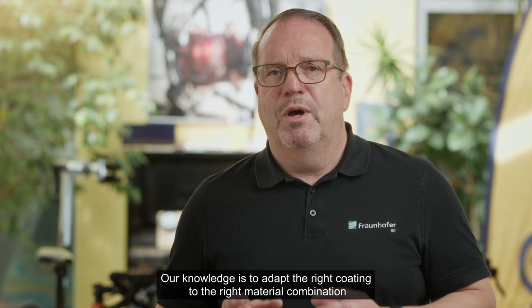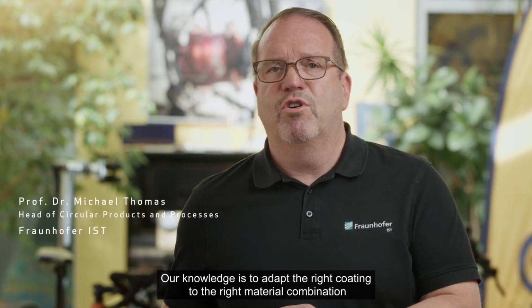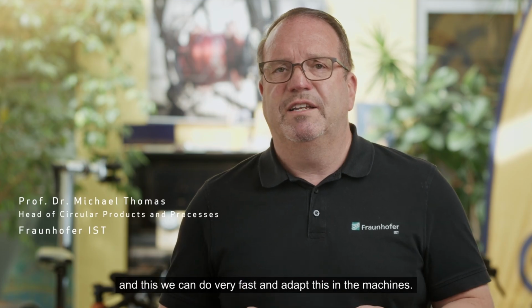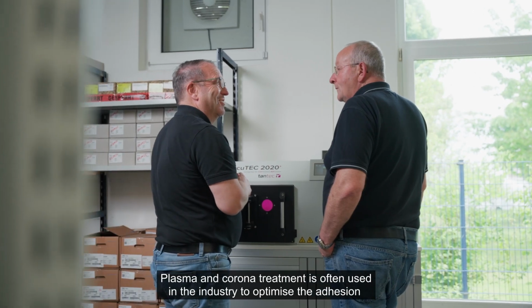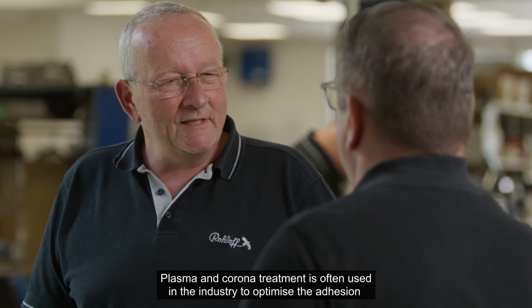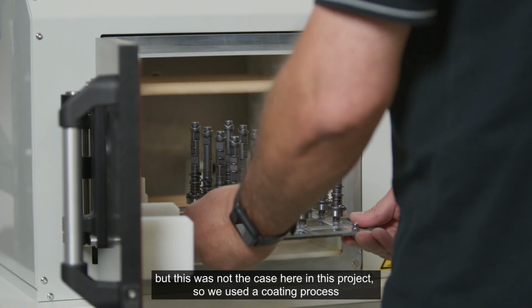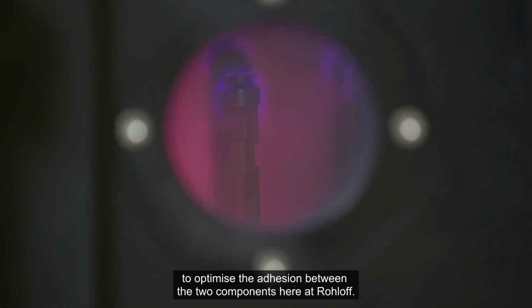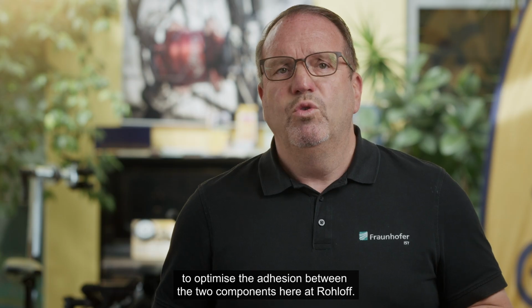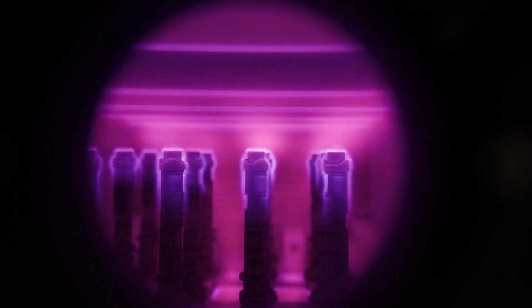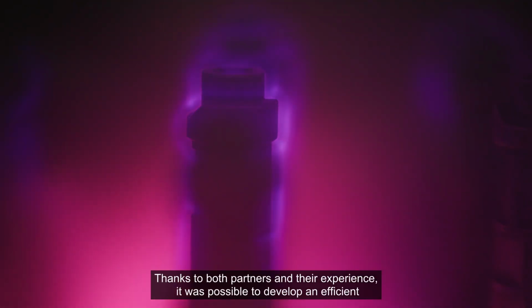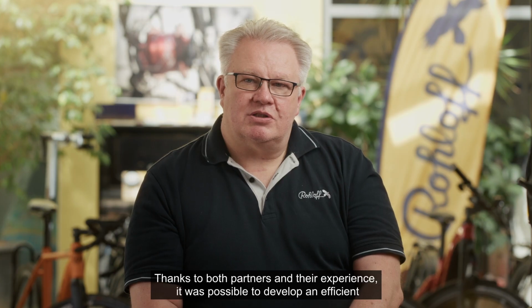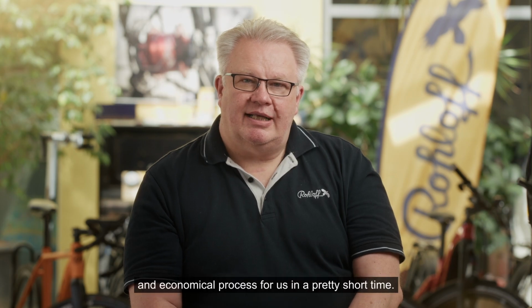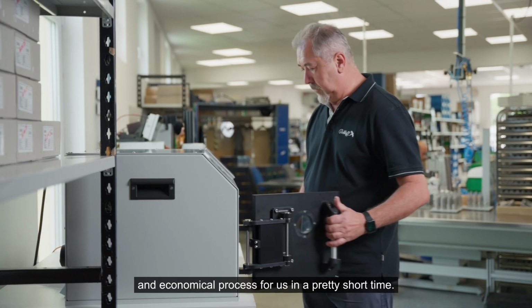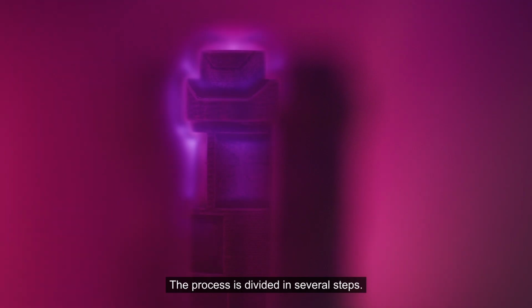Our knowledge is to adapt the right coating to the right material combination. And this we can do very fast and adapt this in the machines. Plasma and corona treatment is often used in the industry to optimize the adhesion. But this was not the case here in this project. So we used the coating process to optimize the adhesion between the two components here at Rohloff. Thanks to both partners and their experience, it was possible to develop an efficient and economical process for us in a pretty short time. The process is divided in several steps.